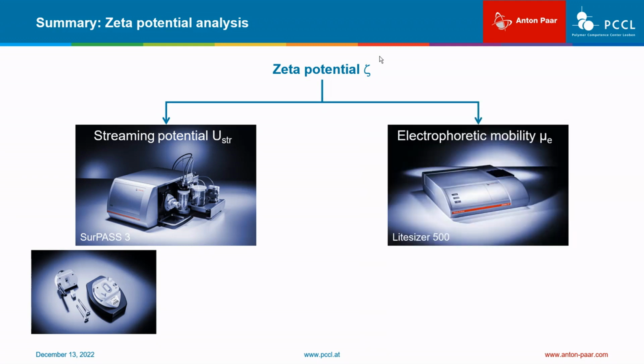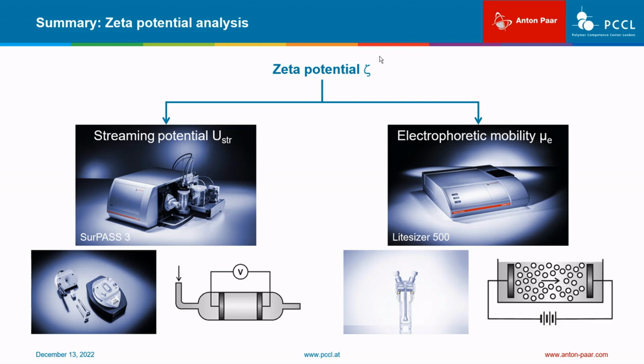The Zeta potential in colloidal dispersions of particles is determined from the measurement of the electrophoretic mobility with the instrument Litesizer 500. Liquid samples are injected in the omega cuvette, which is shown as a representative sample holder. Remember the difference in the measuring principles of these two approaches. For the streaming potential measurement, we apply a pressure gradient along a capillary flow channel or along a porous sample, while for the measurement of the electrophoretic mobility, we use an electric field as the driving force for moving charged particles in dispersion.